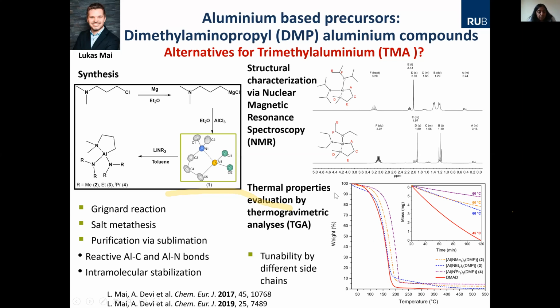So here you can see a graph where you have the weight of the precursor measured as a function of temperature. So you have to take a precursor in a small crucible and heat it. After a certain temperature, you see the weight loss occurs. That means the precursor is losing weight, and it continues to high temperature. At certain temperatures, there's nothing left in the crucible.